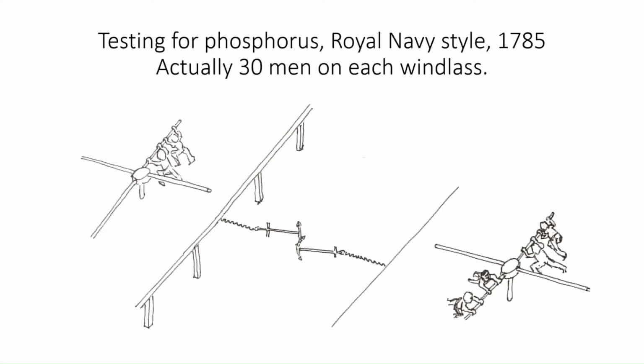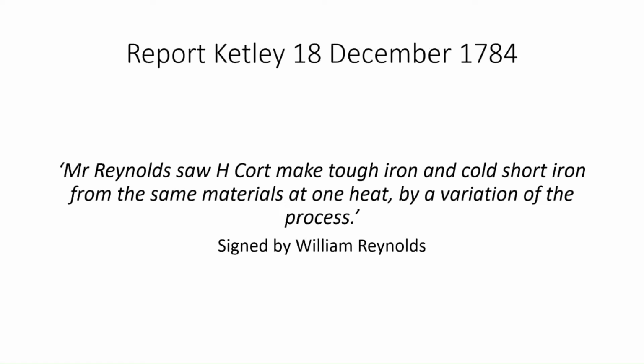But then there's another fascinating part of this, because it's not immediately obvious how the puddling process removed phosphorus. Now, people know about the chemistry of phosphorus. If you oxidize it and you run it at a low temperature, then you can get a distribution between the iron and the slag, which improves as you lower the temperature. But when Henry Cort demonstrated this to William Reynolds, who was the son of Richard Reynolds that we mentioned before, Abraham Darby II's grandson, he said that Henry Cort could actually make the iron tough or cold short just by changing the process. And what I'm hoping to do is discover how it was that he did that, because it's not immediately obvious.